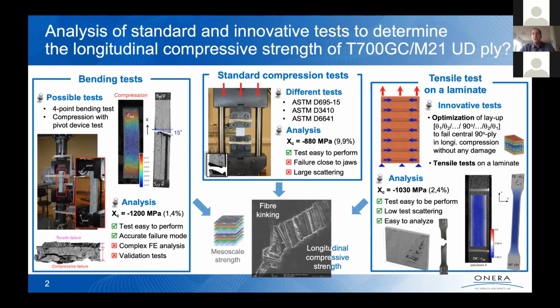So we have applied such a strategy to the T700 M21, and we have observed pretty nice fiber kinking in the specimen. You can see here what we have observed using CT scan or SEM observation. We were able to measure the average strength, which is pretty high, minus 1000 MPa. But the point which is really important is that the scattering associated to such a test is very low. Why? Because in fact, the maximum strain and the maximum stress are located at mid-width of the specimen, far from the edges. Because in fact, the loading is introduced through the blocked Poisson effect. So because we are far from the edge, the scattering is pretty low and close to the real scattering of the material.